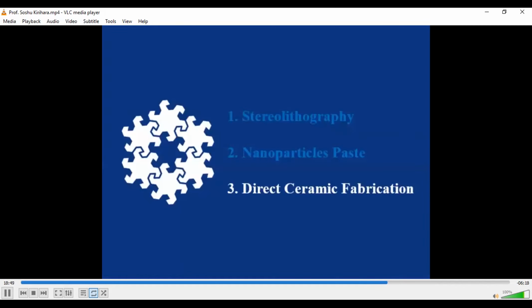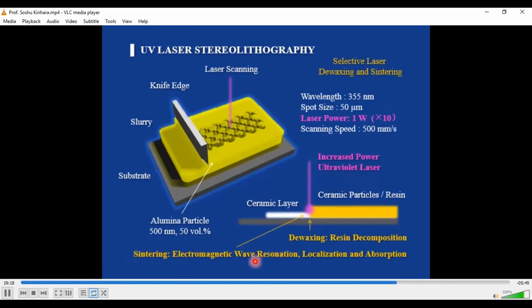So the next trial is direct ceramic fabrication by using a laser scanning process. In this case, the ultraviolet laser beam power is increased to 1 watt. This is 10 times higher compared with the conventional stereolithography process. So increasing the ultraviolet laser beam power realizes dewaxing, resin decomposition, and sintering by using electromagnetic wave resonance, localization, and absorption.